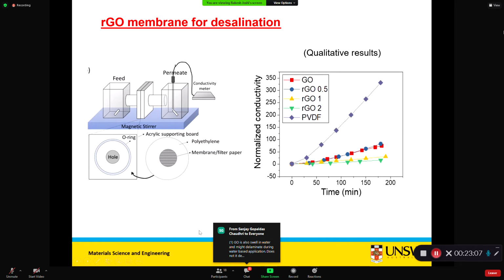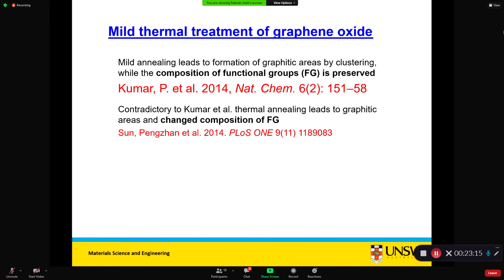So we did enlarging the porosity and then reducing the porosity; we did both. And we saw that when you heat graphene oxide in different situations, it can give different properties. So we did more literature survey and came across these two papers. One says that if you anneal graphene oxide, there was a very nice article in Nature Chemistry from an MIT group. They say that the composition of the graphene oxide will not change, however the graphitic regions will be larger. The other paper is from Hongwei's group at Tsinghua University. They say they can see the graphitic areas getting larger, but also see the composition changing. So we thought of repeating both experiments.